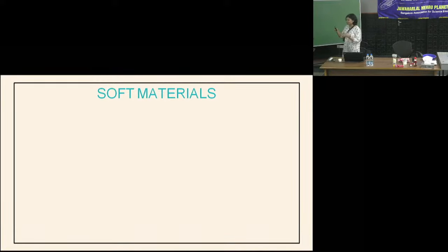And so we're using clay. They make glasses, in that they show all the properties of glasses that you'd otherwise expect in, say, window glass. For instance, two relaxation times, the alpha and the beta relaxation times. Also, if you can somehow melt the glass and then quench it again, it's going to start evolving into a new kind of glass. This is called rejuvenation. We do all that in the lab.